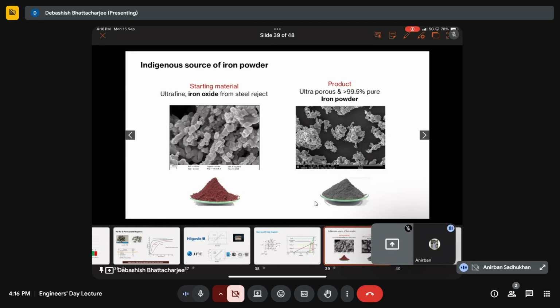The steel that gets into car bodies is almost pure iron, very low alloying contents. They're called interstitial free steels. So very low carbon, very low nitrogen, because if you add alloying elements, they become strong and you can't form them. So they're almost pure. If you take that rust, which is almost pure Fe2O3, and reduce it with either hydrogen or ammonia, not carbon, then you get almost pure iron, 99.5% and above.